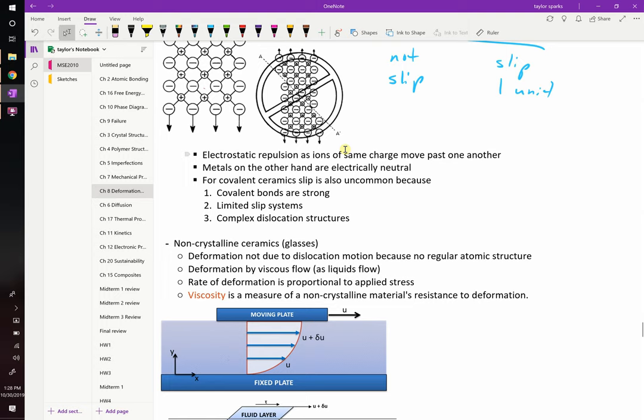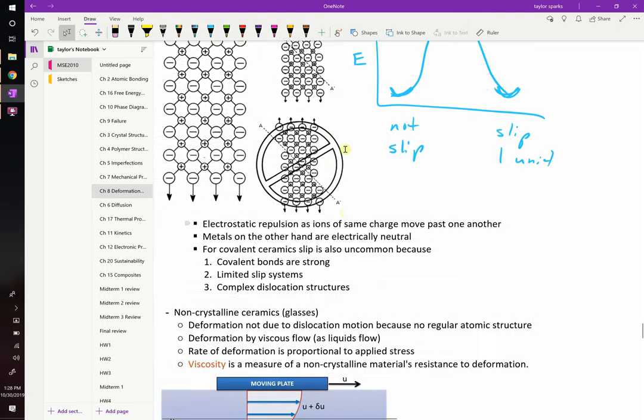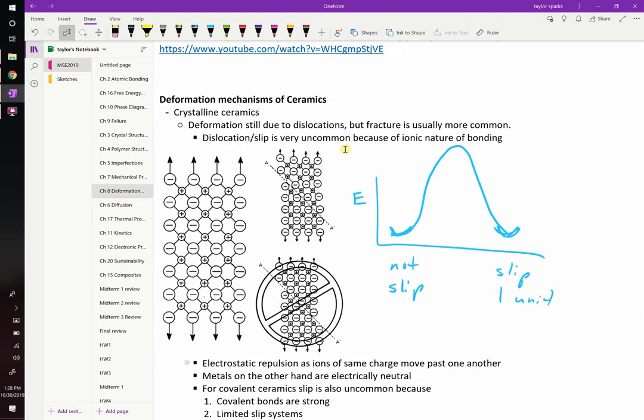Now, covalent systems, let's say you're not an ionic ceramic. Let's say you're something like diamond. Diamond is not ductile either, because in diamond, it's even worse, actually. Because imagine what's happening in diamond. Instead of having this picture where it's positives and negatives, where these aren't really directional bonds, there's just this positive-negative attraction. In diamond, this is a strong covalent bond. That's a carbon bond with another carbon. So you don't want to break that bond to slide it over. You'd have to form another bond in doing so. We have to break a really strong bond first, which is why it's also brittle.